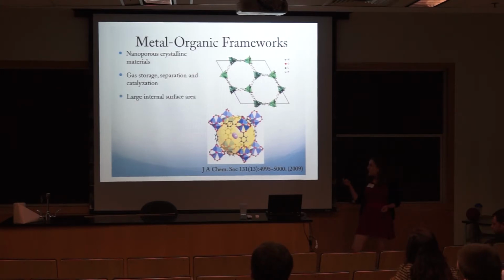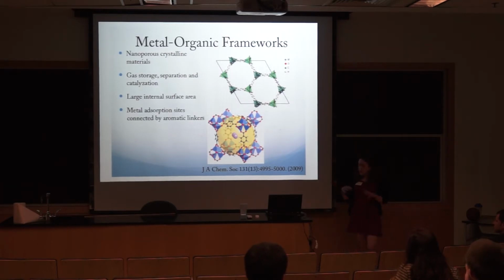We have a very large internal surface area. Here the yellow is the space that the hydrogen has to go into the MOF. I kind of think about it as a sort of molecular sponge, so it just soaks everything up. The metal organic frameworks are made of metal adsorption sites, so the metal part, and then organic linkers. These are aromatic linkers. In our materials, they're usually benzene rings.